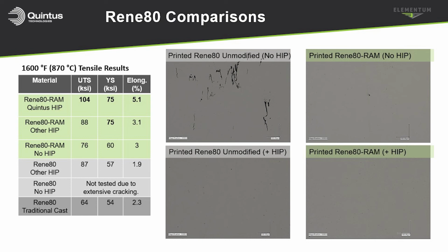You can combine that now with the solution treatment and the aging that's needed for those alloys to get the right properties because of the rapid cooling that the Quintus systems allow. So that full in situ heat treatment and HIP approach, we found that there's significant property improvements here.